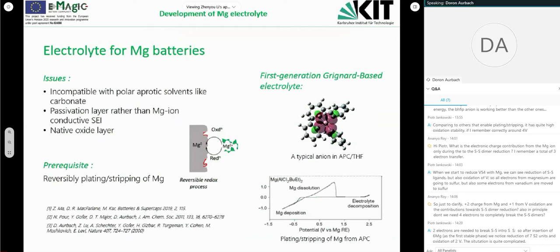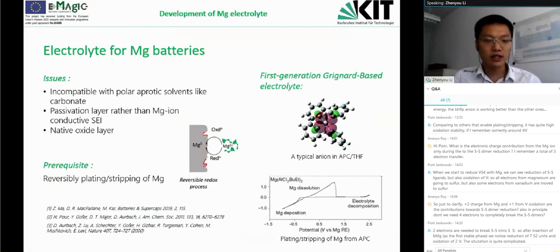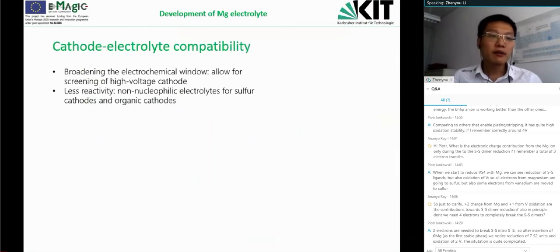The first generation of magnesium battery that could deal with this problem, or realize the reversible magnesium stripping and plating, is to apply a Grignard-based electrolyte. We know that Grignard agents are reactive, and they can react with moisture and oxidant species in the electrolyte solution, and could also clean the magnesium surface. And with the addition of chlorine species, we have the well-known APC electrolyte reported by Professor Aurbach's group. With the addition of chlorine, we have an extended electrochemical window, and we also have better ionic conductivity.